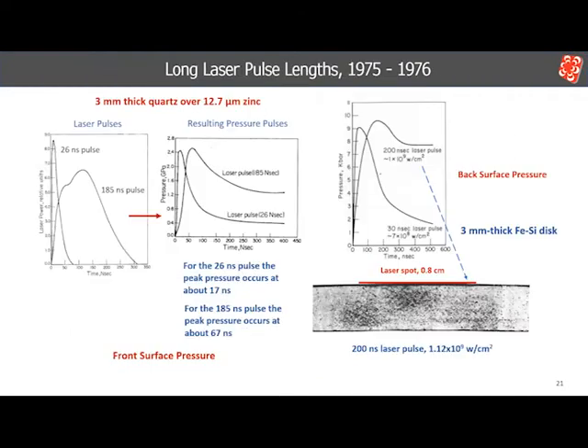We also took a look at comparing the effects of short laser pulses to much longer laser pulses. On the left, we show a comparison between measured short and long laser pulses and the resulting pressure pulses for a zinc and 3mm quartz overlay. Because of the longer rise time in the long pulse, the pressure peak occurs much later than in the short pulse. The 185 nanosecond pulse maintains a sustained pressure of about half the peak pressure for over 400 nanoseconds.